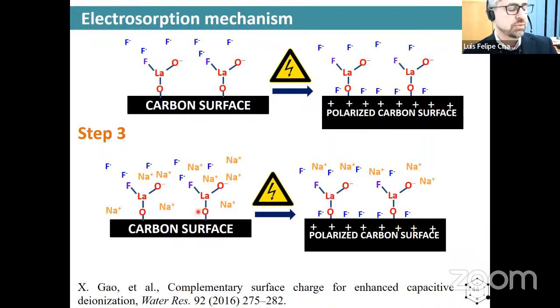So then there is a synergy between the inner potential, I mean the applied potential of 0.8 volts, and the surface potential associated with electrode surface chemistry. So the global attraction towards fluoride increases when both potentials are more positive, and also the step of adsorption equilibrium is very important, no? As a previous step. And additionally, it is known that the lanthanum can expand its coordination sphere. I mean, the lanthanum can accept more than 2 fluorides, no? And this is very well described in the literature.